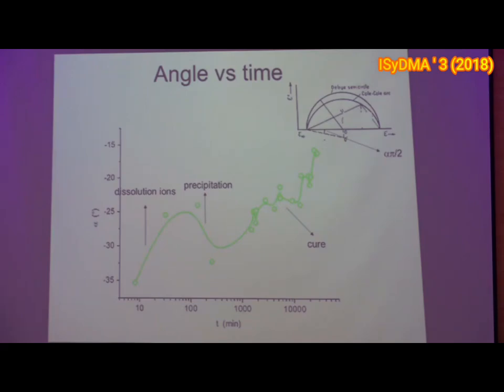When I have alpha close to 0, that is, if I am in the Debye process, the system must be homogeneous, and we must not have dipole interactions between different dipoles. So here I see that the angle increases, starting at 35 and increasing. This means that this point here is going up, so it is closing in on the Debye model. That is, the cement is becoming more homogeneous with time, which is logical.